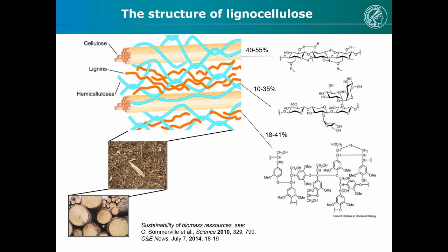It means that all the glycosidic bonds, these bonds here which connect glucose rings, are extremely well protected by this sheet structure. And so the cellulose is very difficult to depolymerize. On the other hand, it would be really interesting to depolymerize cellulose. In the early 20th century, so 1910, people really wanted to so-called saccharify wood, making sugar from wood, because this is the main constituent of wood. Most of the wood here is actually glucose in a polymerized form. If you can split it, you have sugar. And that would be much cheaper than having sugar cane or sugar beet or whatever.